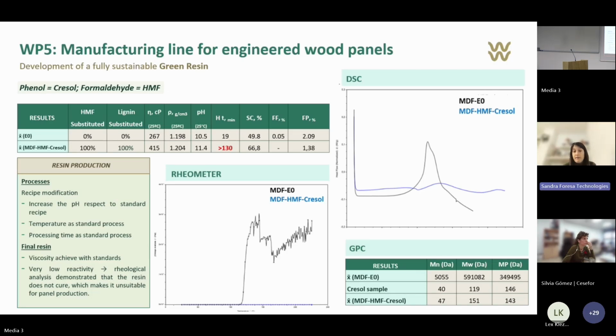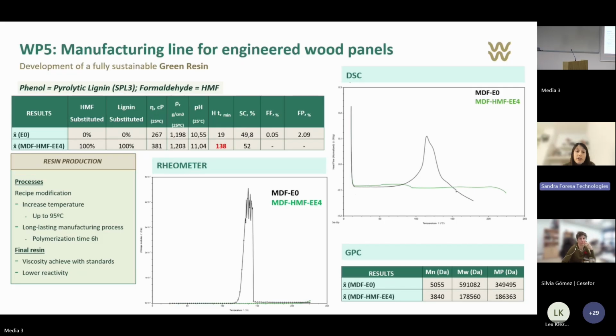So we switched the cresol for pyrolytic lignin, maintaining the HMF, to elaborate the 100% bioresin. In this case, we had to modify the standard recipe, not only increasing the pH at the beginning of the reaction to avoid precipitation, but also the temperature. The temperature had to be drastically elevated, around 95 degrees, for the polymerization stage. Implementing this modification allowed us to achieve a viscosity similar to the reference.